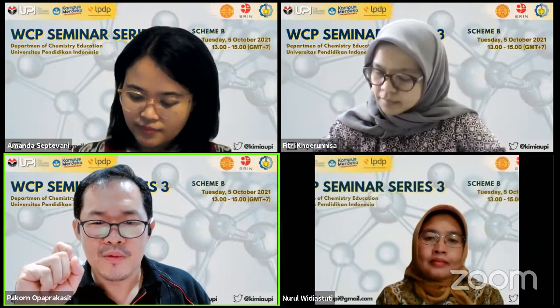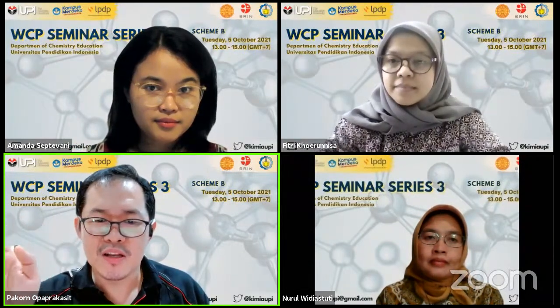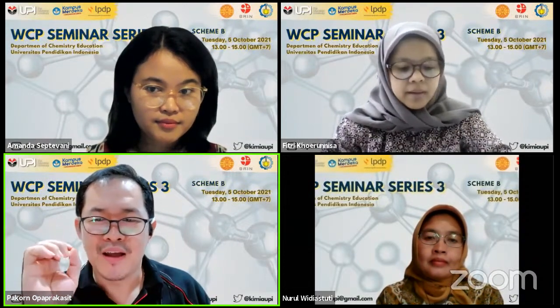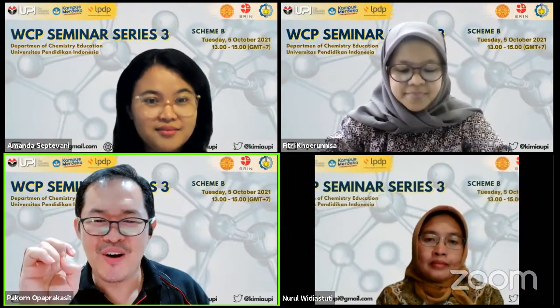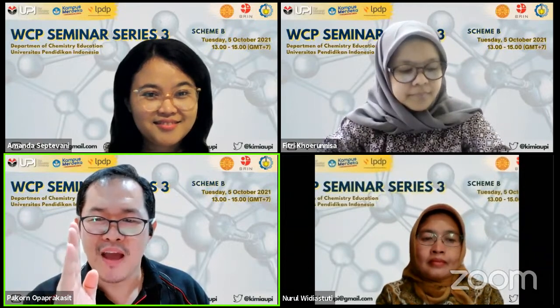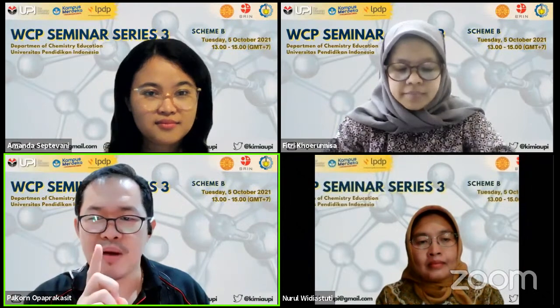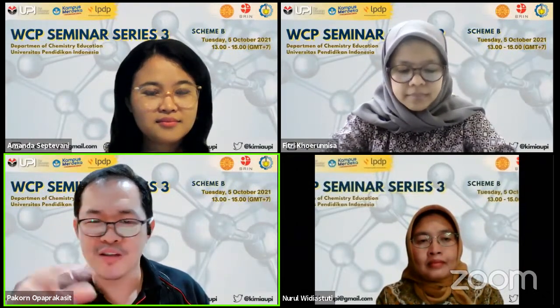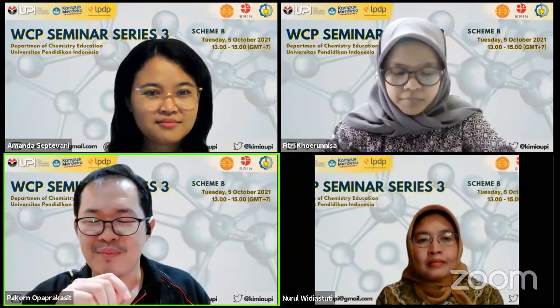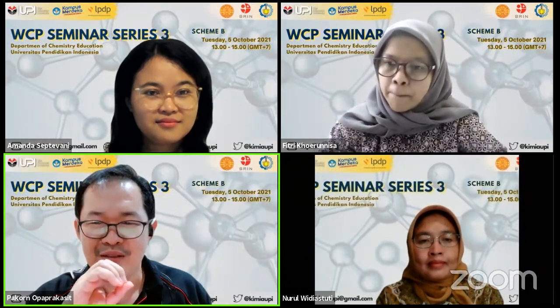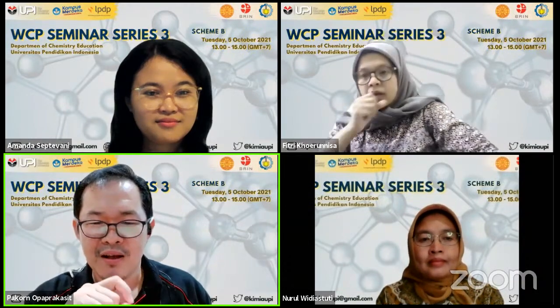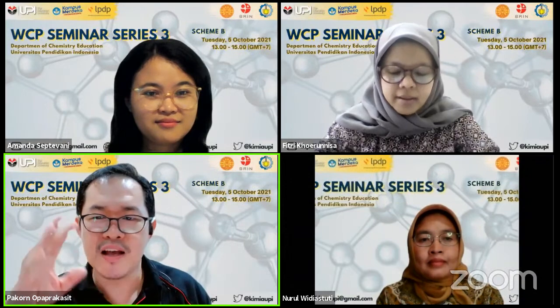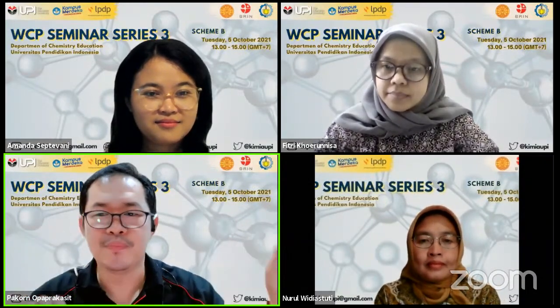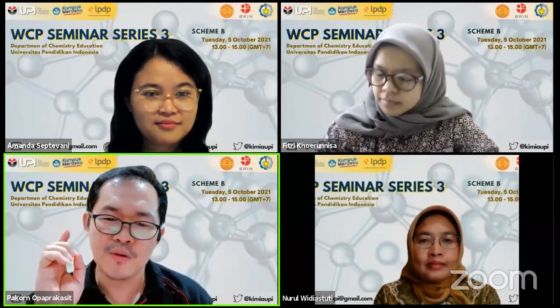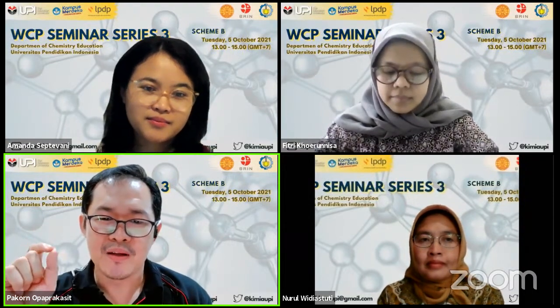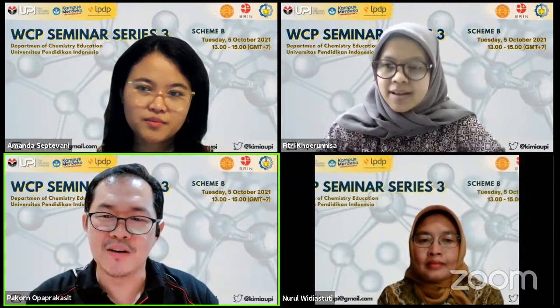However, if you worry about the depth of penetration at different frequency, this will happen the same way to all samples. Therefore, across samples you use a certain band as a reference and you normalize your whole spectra by the reference band. You can then compare other bands across samples conveniently. So I can say that ATR is a very, very common technique for doing quantitative analysis, especially if we compare similar samples. It may be hard to compare different samples. But if we do quantitative analysis, we need to make a standard curve from the same type of materials. So ATR is the ideal solution.